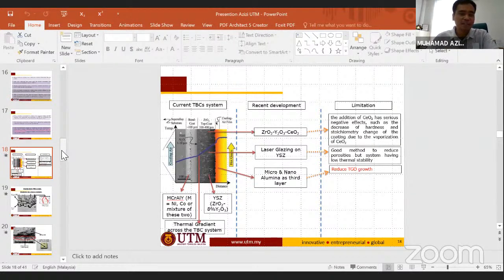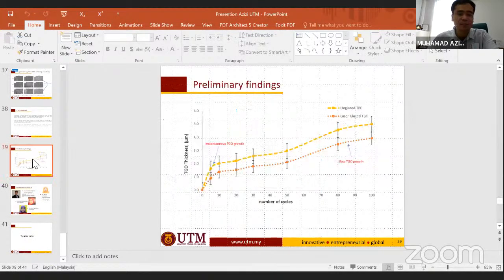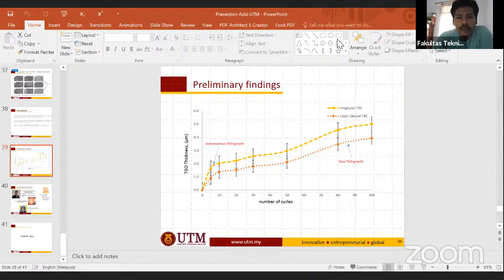Okay. Based on the current investigation, we found that there is a significant effect. If you look at this graph, without glazing and with glazing, there is around 20 or 30% reduction of TGO thickness, because TGO is very, very crucial in TBC. Yeah, I understand, because if we have a thick layer, the possibility of having porosity is higher than in a thin layer.